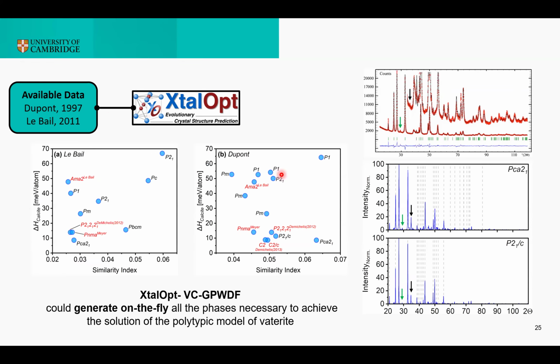With the database by DuPont, I obtained a similar result, but of course not identical. So most of the phases here were found together with new ones. But most importantly, I could find the C2 and C2 over C phases that are actually composing the polytypic model that I was showing before. And so this also shows the importance of the quality of the experimental data to run theoretical models.